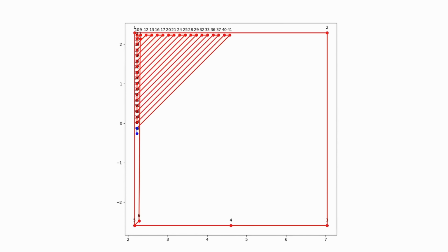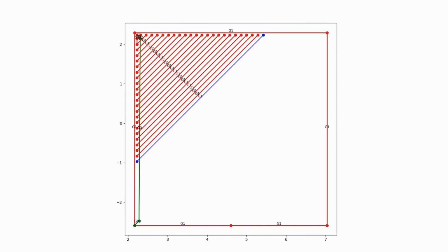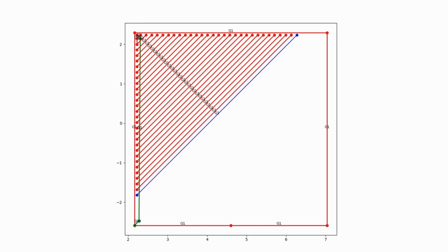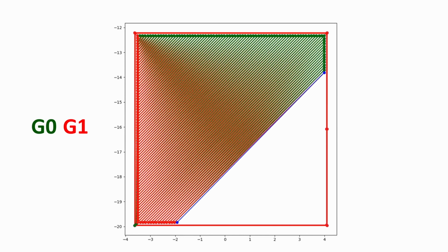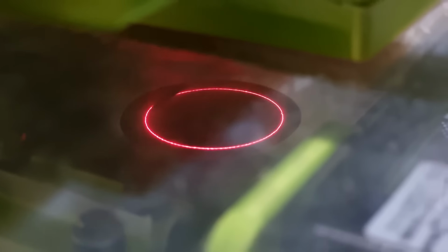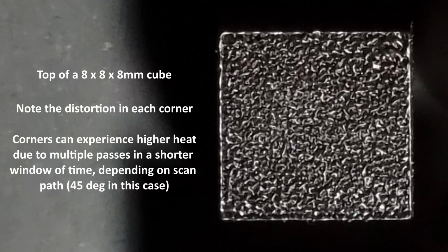I would like to think that if I revisited that approach, I would come out better off second time around. After witnessing the creation of the edges from the adjoining segments, I decided that I'd rework the post-processing script so they would no longer exist. I also modified the script so that it would only generate a unidirectional scan pattern, simply to avoid horseshoeing, attempting to generate a more uniform heating strategy.